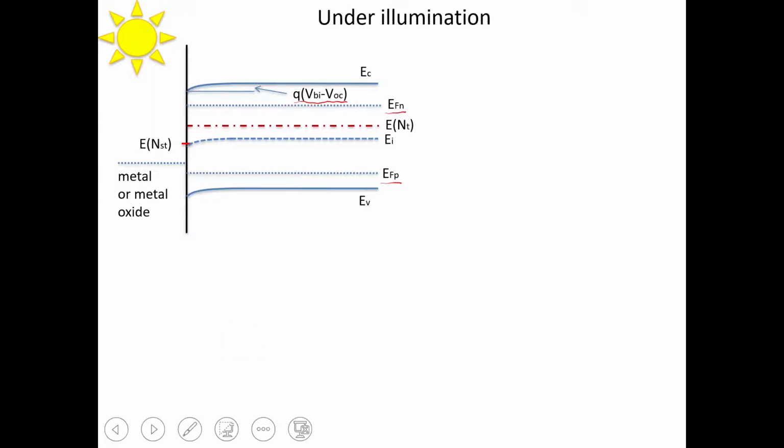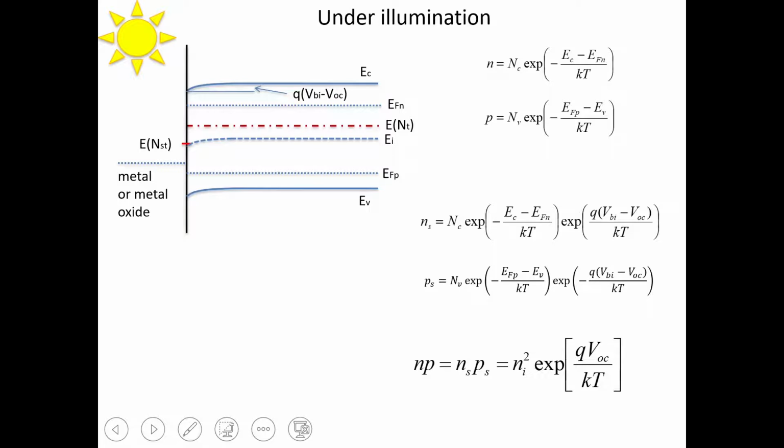So, in order to proceed further with the recombination at the interface between metal and semiconductor, we need to learn about charge carrier concentration, like total charge carrier concentration at the interface. So first we have non-equilibrium, like total equilibrium plus non-equilibrium charge carrier concentration given in the bulk of the semiconductor, where we don't have any band bending, in terms of quasi-Fermi energy levels for electrons and holes.